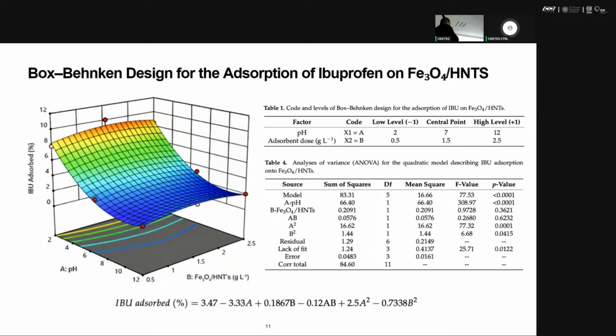And it is very useful because this statistical model gives me an empirical equation that quantitatively describes the method, and it gives you a value which I can compare for every experiment. So here I found that the best condition for the absorption was a pH of 2 and an absorbent concentration of 1.5 grams per liter. Even so, this is not a good result, because the maximum quantity of ibuprofen absorbed was around 10%.